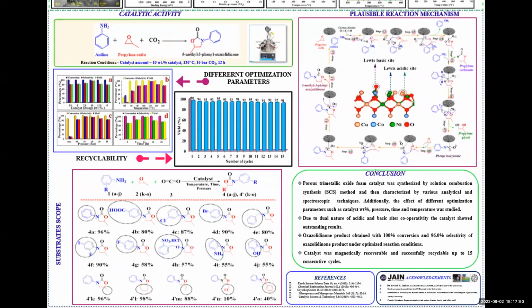I am concluding my presentation. We successfully synthesized the porous trimetallic oxide catalyst by the solution combustion synthesis method and well characterized it by various analytical and spectrochemical techniques. Additionally, we studied different optimizations of reaction parameters such as catalyst weight percent, pressure, time, and temperature. Due to the presence of acidic and basic site cooperativity, the catalyst showed outstanding results. This catalyst showed 100% conversion and 96% selectivity of the desired product, oxazolidinone, under mild reaction conditions. And this catalyst is magnetically recoverable and successfully recyclable after 15 consecutive cycles.